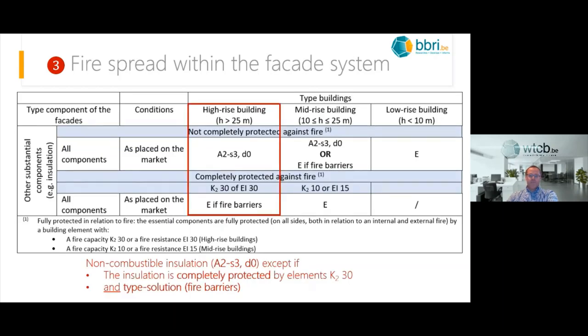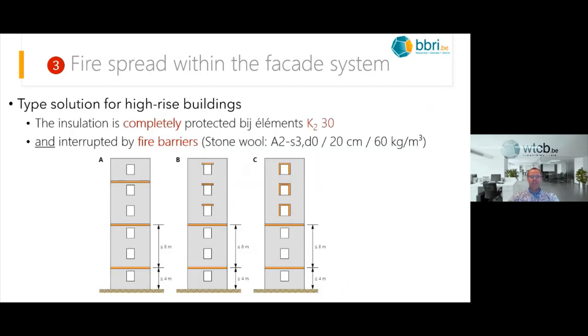For high-rise buildings, the insulation shall be non-combustible, with a reaction to fire class A2-s3,d0, unless it's completely protected by elements K2 30 or EI 30, and the condition of the high-rise building type solution is fulfilled. So you will have to use non-combustible materials, or you have to protect all the materials, and for the type solution you also need a fire barrier. You can see that in this figure.